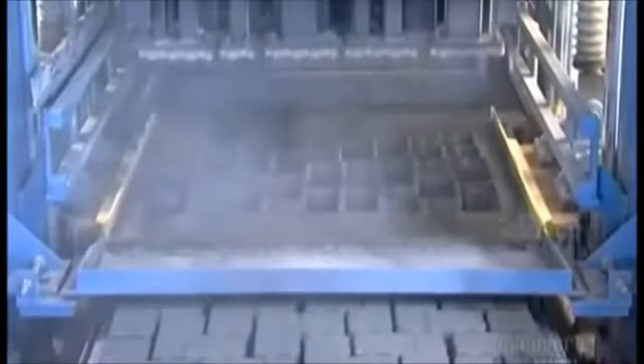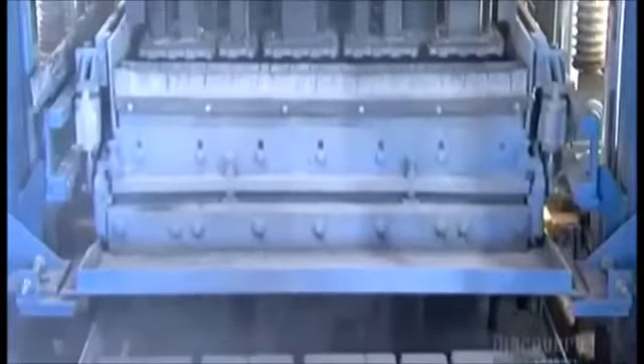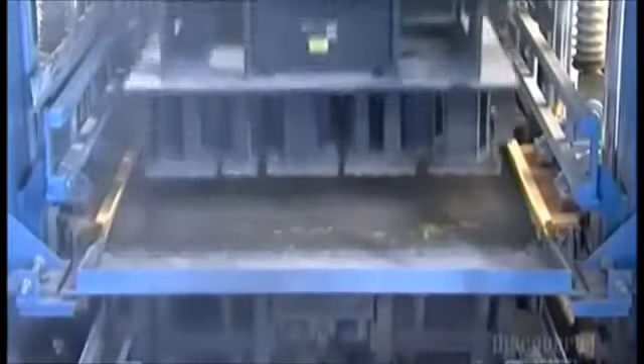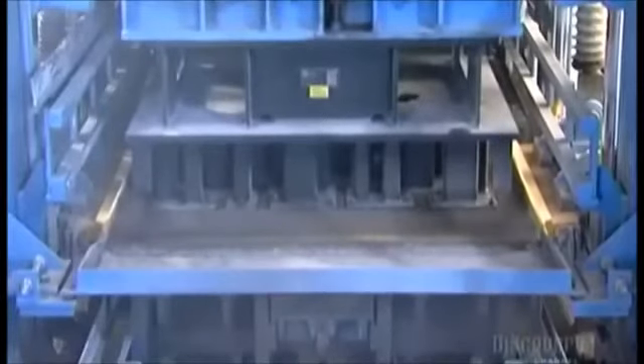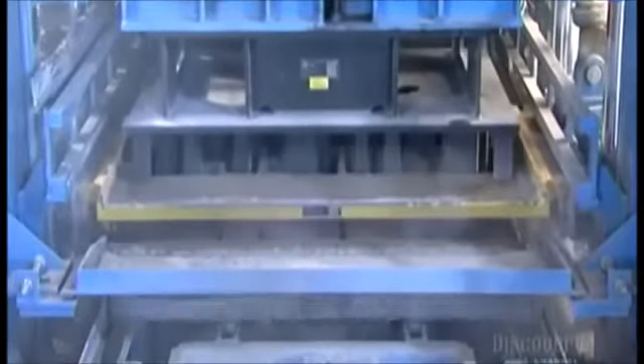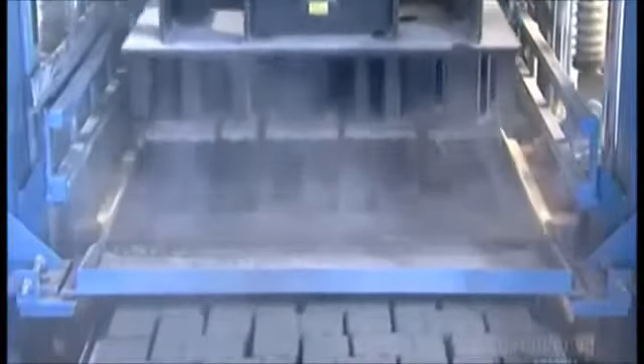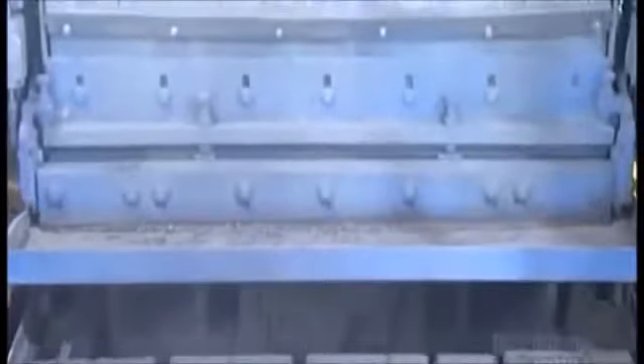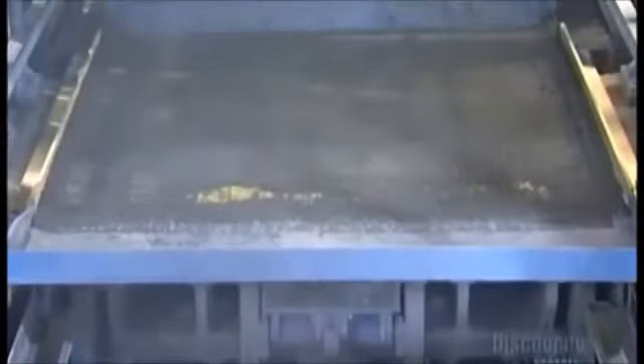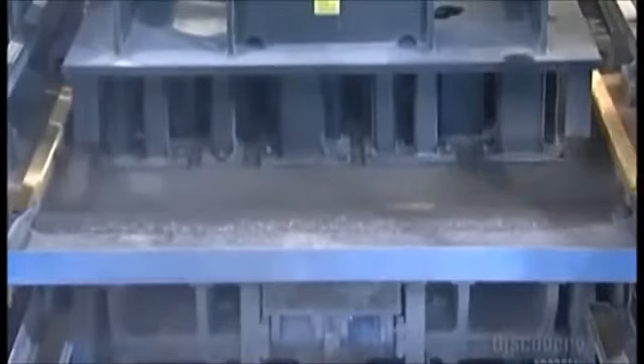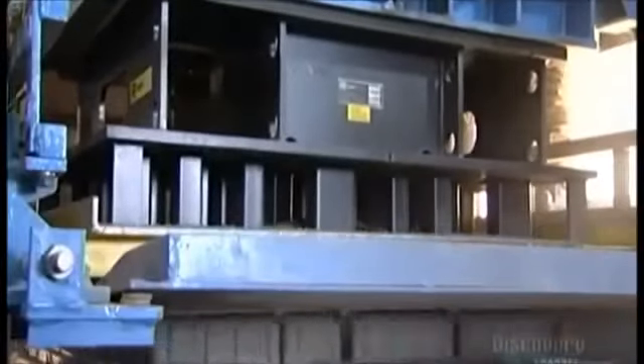Now a filling wagon spreads the mix over a steel mold containing up to 50 paver-shaped cavities. The mold press head applies 10 tons of vibrating pressure. This pulsating force compacts the mixture into the paver mold and removes any air pockets, which could weaken the pavers. Hydraulic cylinders lift the mold, leaving the pavers on the press board. The press board slides out, and the mold once again gets filled in and makes another 50 paver stones. It only takes about 10 seconds to mold, compact, and release a batch of pavers.